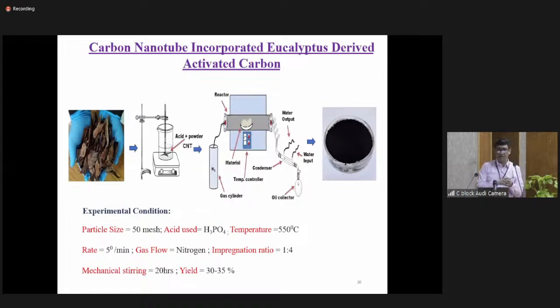So what we did basically, initially in some experiment, we took the eucalyptus bark and then mixed the carbon nanotube simply and then used it. But it was not successful. It was not enhancing any property. Because there are two different phases, okay, somewhere there is carbon nanotube, somewhere the activated carbon, not properly mixed.